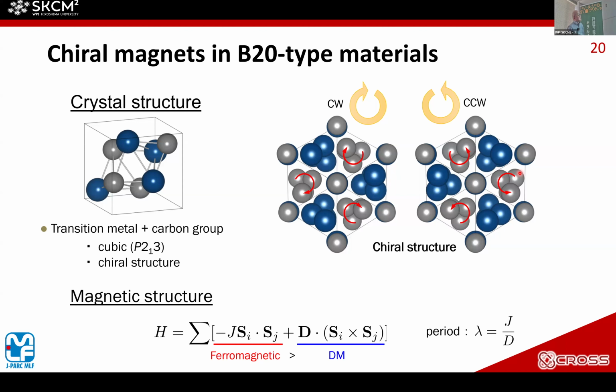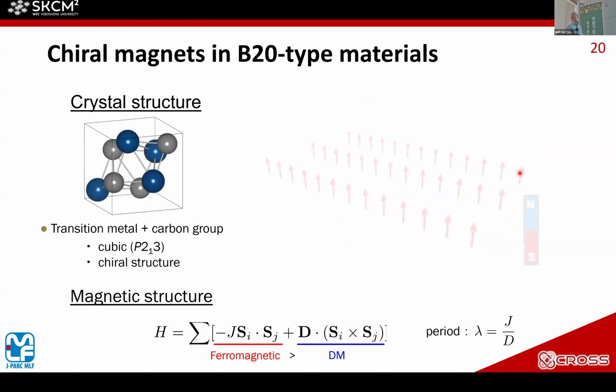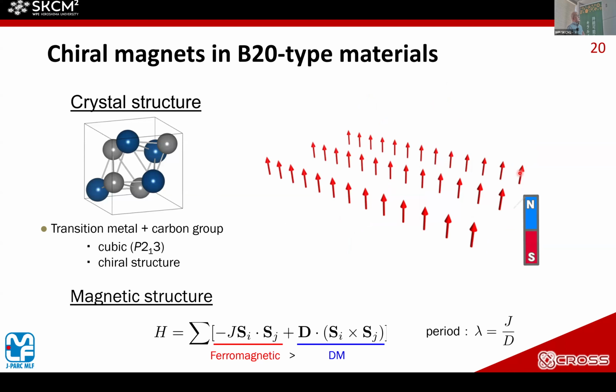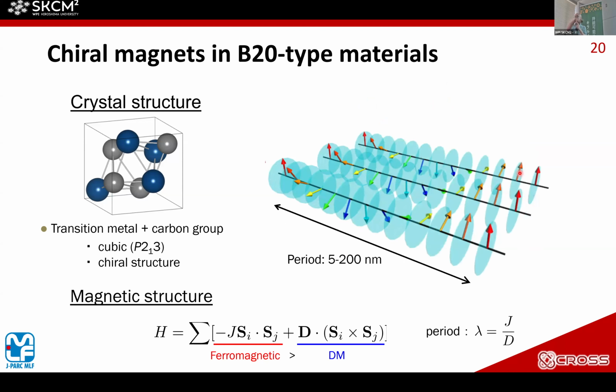And in these chiral structures, the magnetic structure is also affected by this chirality. So in this case, an asymmetric interaction, the so-called Dzyaloshinskii-Moriya interaction, appears, and it competes with the exchange interaction. For example, when the exchange interaction is ferromagnetic, then a non-chiral material makes a ferromagnetic state below the transition temperature. But in the chiral magnetic case, because of the Dzyaloshinskii-Moriya interaction, which twists the next neighbor's spin, the magnetic structure takes a spiral structure.